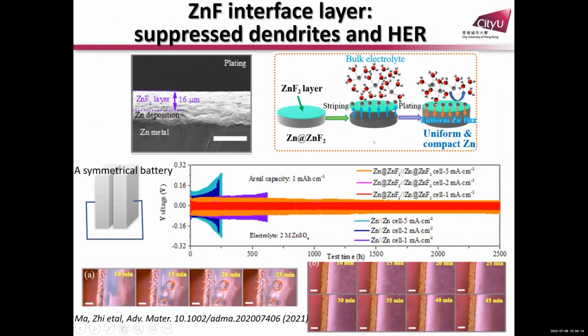Then we changed to another material, zinc fluoride. This is copied from lithium-ion batteries, where fluoride always gives you stability and can be conductive for the ions. We synthesized zinc fluoride on the surface and used symmetrical batteries to test up to 5 milliamperes per square centimeter, with pretty good stability. And this layer is not electronically conductive, so it can avoid electric conduction between zinc and water. If you don't have this coating, you get hydrogen bubbles.